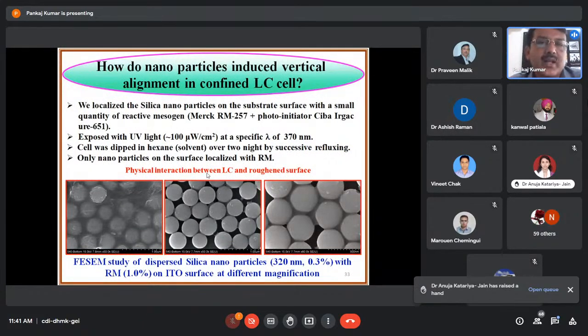Even in one of the slides, we have emphasized that the liquid crystal molecules and the nanoparticles are going to the surface, and they are modifying the surface, and with this modified surface the liquid crystal molecules are going vertical. So for the confirmation of this experiment or our thought, we localized the silica nanoparticles on the substrate surface with a small quantity of reactive mesogen, that is RM257 plus photoinitiator, and we exposed these with UV light at 100 microwatts per square centimeter at a specific wavelength, lambda 370 nanometer.